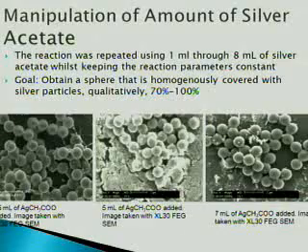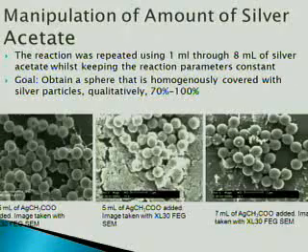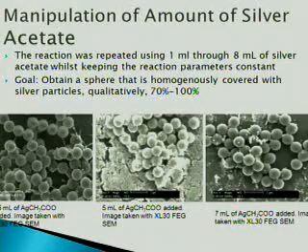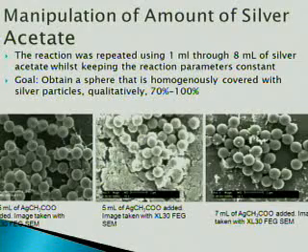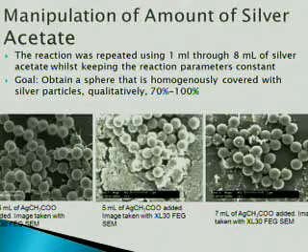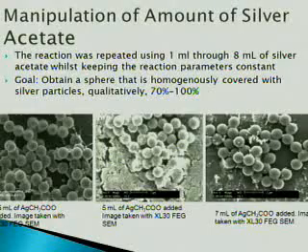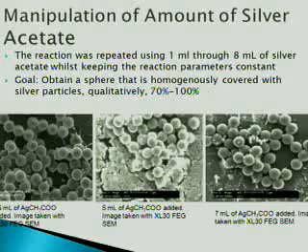As you can see from the pictures, the most optimal amount of coverage was from 5 milliliters of silver acetate. Anything less — as you can see from the 2.5 milliliter sample — resulted in insufficient silver present, so not enough was deposited on the spheres. Anything over 5 milliliters, as you can see from the 7 milliliter sample, resulted in agglomeration of silver off the spheres. This was due to silver undergoing an autocatalytic redox reaction with the reducing agent formaldehyde, creating nucleation sites off the spheres themselves, leaving insufficient silver to deposit on the spheres. So 5 milliliters was the optimal amount of silver acetate.